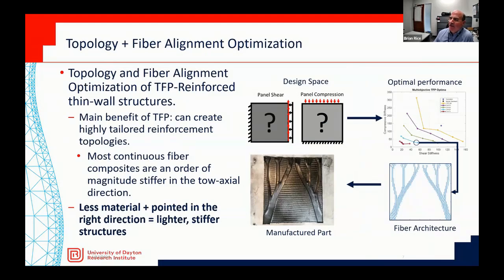We tie that in also with what we call topology optimization. So if you have your FEA model and you know where the stresses are, and you have a technology like tailored fiber placement that can actually locate a tow exactly where you need it, how would you take advantage of this? So here's an example where we were looking at a sandwich structure, two skins with a honeycomb in the middle, which is a very lightweight, stiff structure, but it's not very damage tolerant. How can you make a monolithic skin but still get the same performance in terms of stiffness and weight